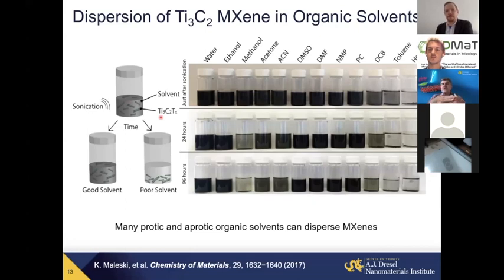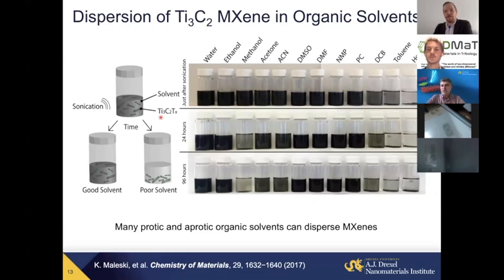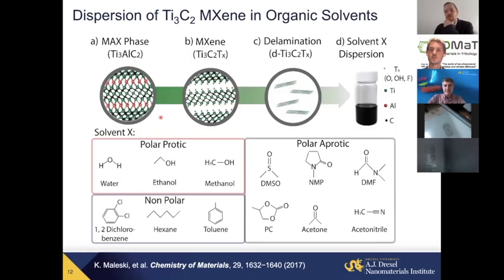They will start to transform into conventional cubic carbide structures or other carbide structures at high temperatures. In air, they're typically stable to temperatures between 200 to 400 degrees C. My feeling is for most tribological applications, that's probably sufficient temperature. They only start losing water or adsorbed molecules at these temperatures. At high temperature, their oxidation starts, but again, it depends on the MXene strongly.